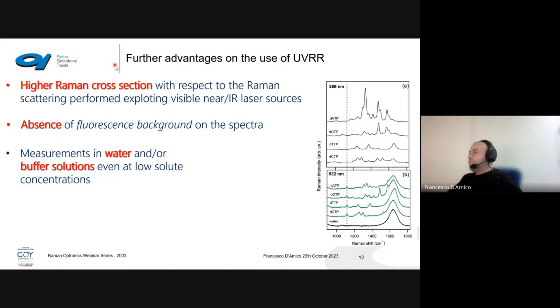For example, here we show several nucleotides measured at 532 nanometers, far from the resonance, in which we see that the spectrum, this is a 10 millimolar solution, is affected by the strong presence of a water peak that also influences the line shape of the spectrum.